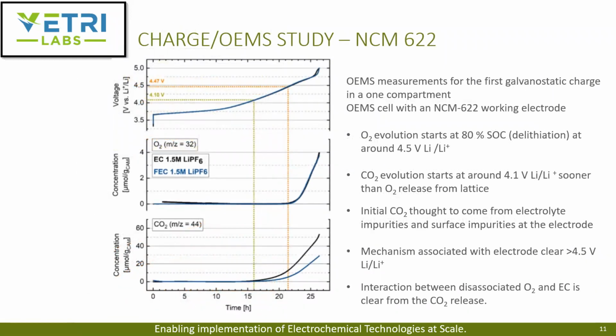This was a charge study with electrochemical mass spec on the NCM 622 cathode material. You can see in that window of 4.1 to 4.5 volts, 4.47 volts, you just about start to see oxygen evolution at that 80% SOC around 4.5 volts.